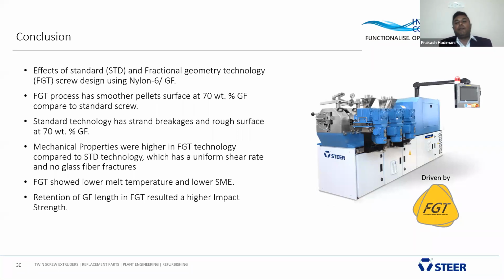You have a lot of processing challenges at 70% because we are running only 30% polymer matrix, and 70% is glass fiber. Okay, you see how challenging it is to process a composite of 70% glass fiber in nylon 6. At the same time, with FGT, all the mechanical properties increase compared to the standard, and we get higher impact strength and higher tensile and flexural modulus using FGT technology.